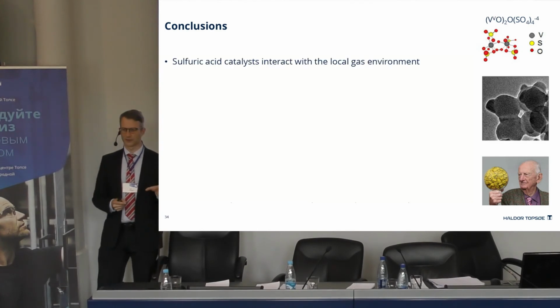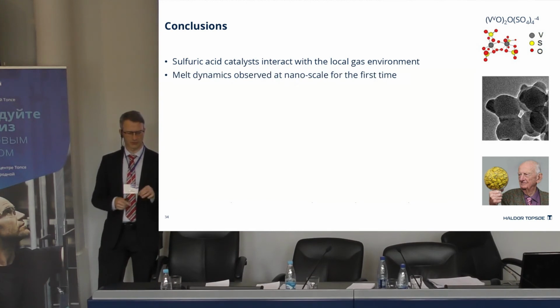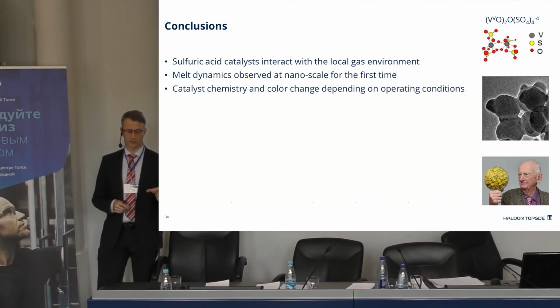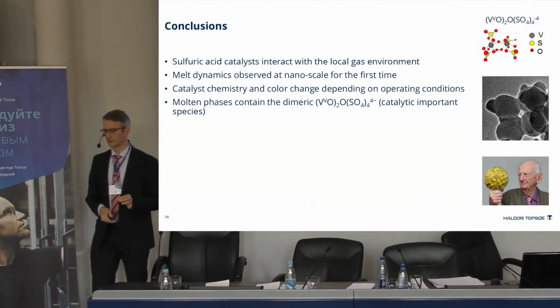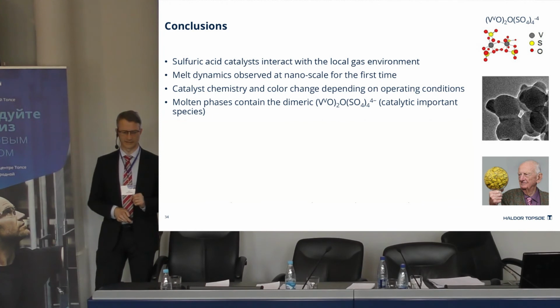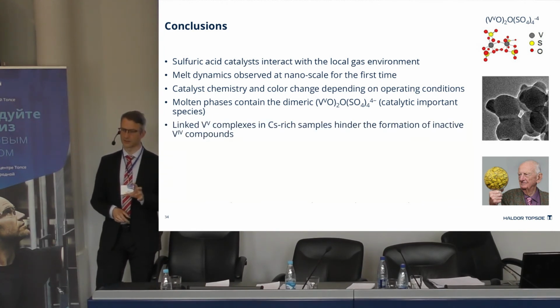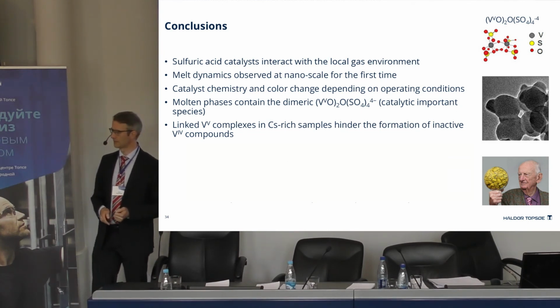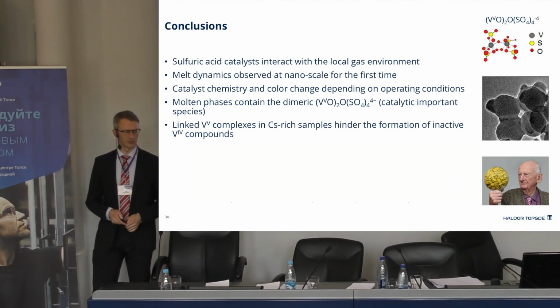So this brings me to my conclusion. I've shown you now how the sulfuric acid catalysts interact with the local gas environment, both vanadium oxidation states and melt distribution. And we have observed the melt dynamics on the nanoscale for the first time. We see the color change when we change operating conditions, and this is due primarily to the vanadium oxidation states, and we've also found the dimeric vanadium oxosulfato complex in there. We've shown that the cesium-rich samples, the cesium-promoted catalyst, can hinder the formation of vanadium 4 and in this way provide high activity at low temperature.